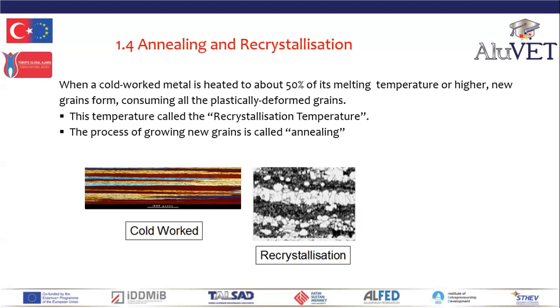So we've got a heavily cold worked structure, as you can see in the picture. If we take it to about half of its melting temperature, new grains start to form. And the new grains grow from the old heavily deformed grains, consuming all those heavily plastically deformed grains. This grain growth process we term recrystallization. This temperature, approximately half the melting temperature of aluminium, we call the recrystallization temperature. And the process of growing new grains from the old cold worked grains, we call annealing.